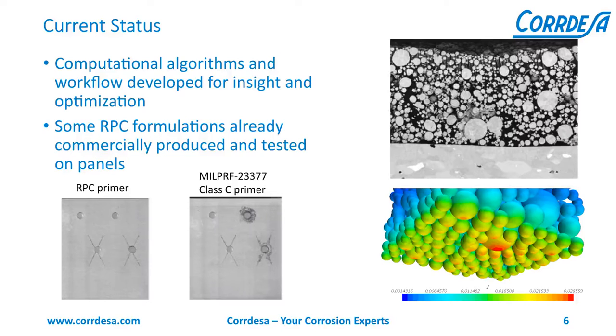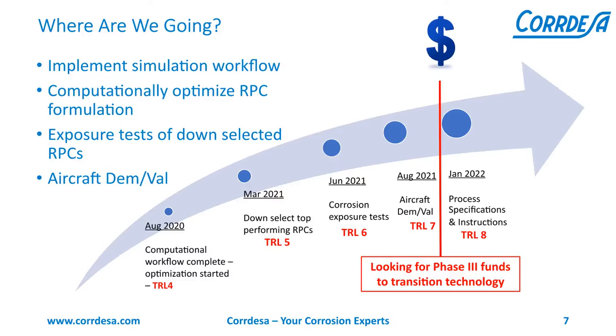Well, an RPC system that has already been extensively tested is the aluminum-rich primer from NAVAIR. In the photograph below, you can clearly see how the RPC primer performs much better than the typical primer system, the scribe panel on the left showing much less corrosion. Corrdesa's proprietary computational algorithms and workflow have provided us with incredible insight into how these sacrificial reactive pigment coatings actually function. In the computer model, we can choose particle size distribution, loading, and resin properties, and then predict the effective protection. In this way, we can optimize the necessary process parameters upfront of any formulation, drastically reducing the timeline for development and testing. So, where are we going with this technology?